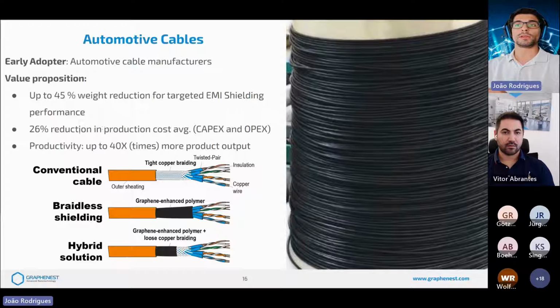So we are able to remove this braiding and replace it with our graphene enhanced polymer, which allows not only for a great weight reduction of the product, but also to reduce the production costs and increase the productivity, since the braiding process is very slow and is no longer necessary. So we can replace it by a standard polymer extrusion process, which is much quicker to produce.